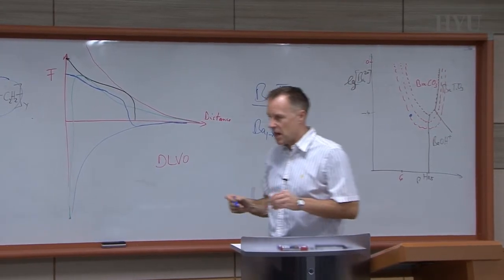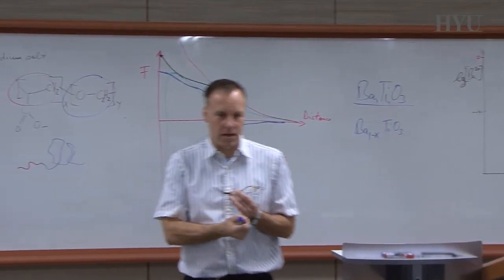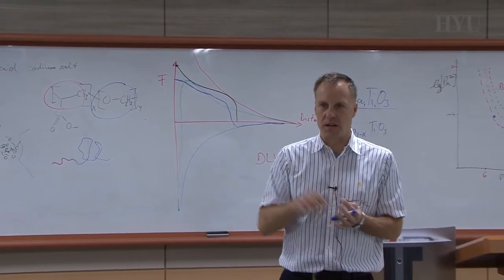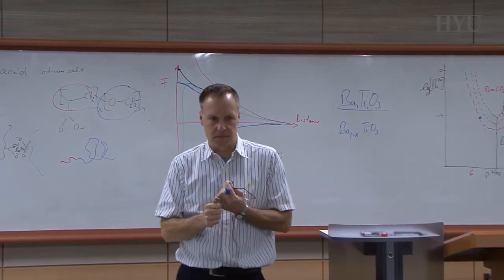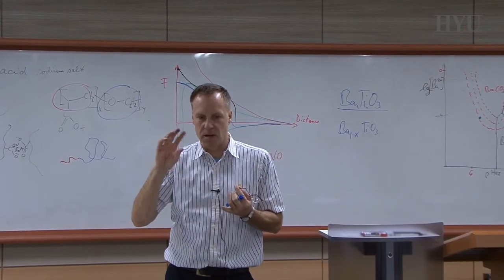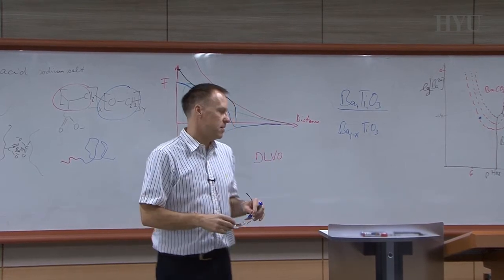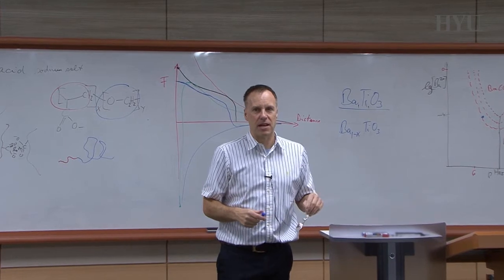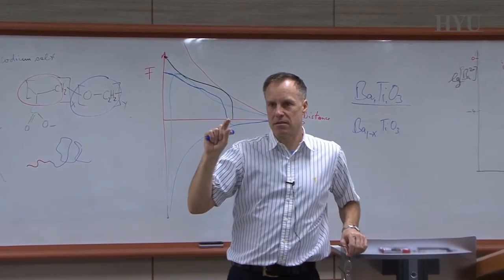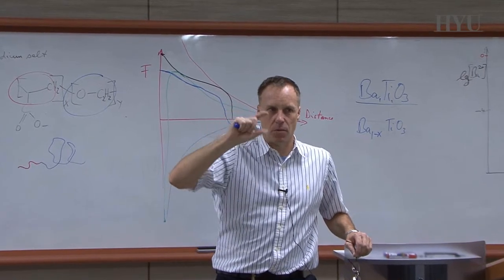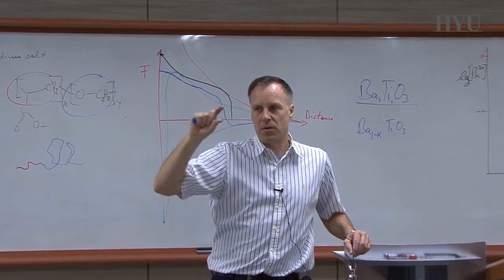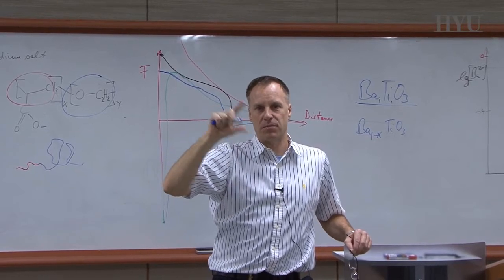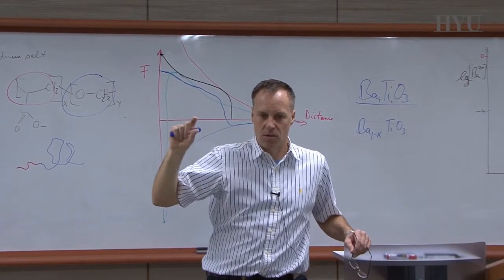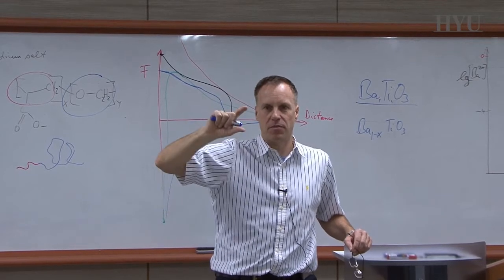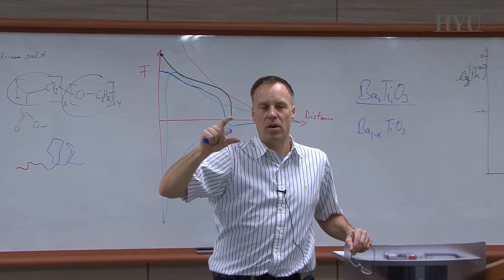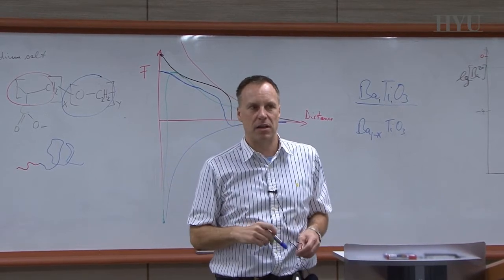So the challenges nowadays, of course, we want to go to more energy stored in a capacitor, so you want to shrink it further, and what we talked about was particle systems. With particle systems, you come down nowadays to around maybe micron size layers. So you use 50 nanometer particles, so you need to stack about 10 particles on top of each other to make a dense film without holes, because holes would allow for dielectric breakdown, and so you don't want to have holes available. So with 10 particles stacked on top of each other, 50 nanometers, the lower limit for particle system is around 500 nanometers per layer.